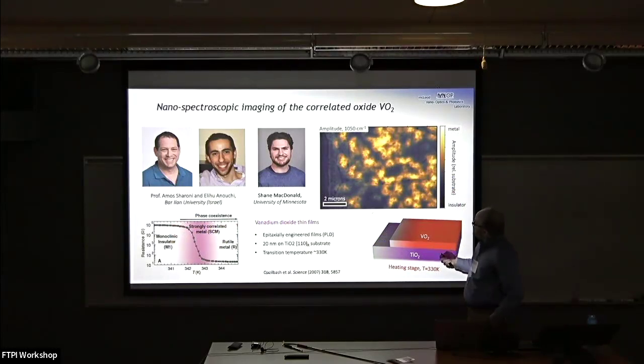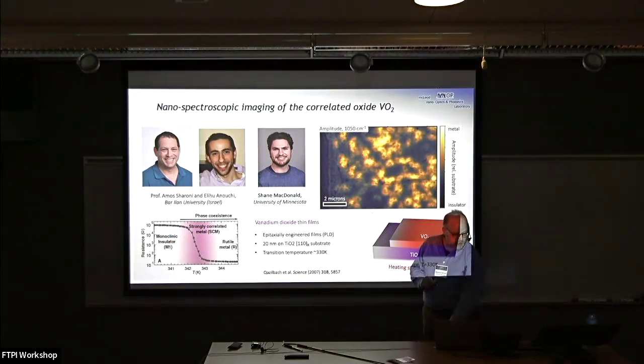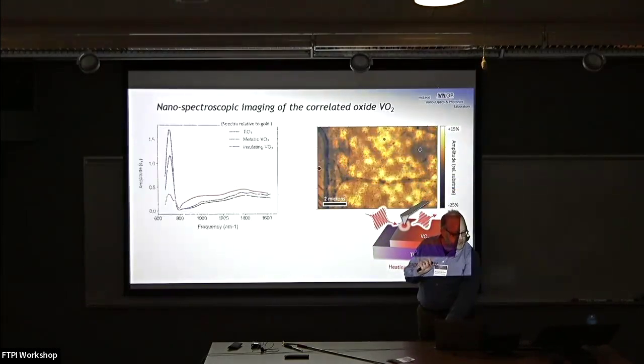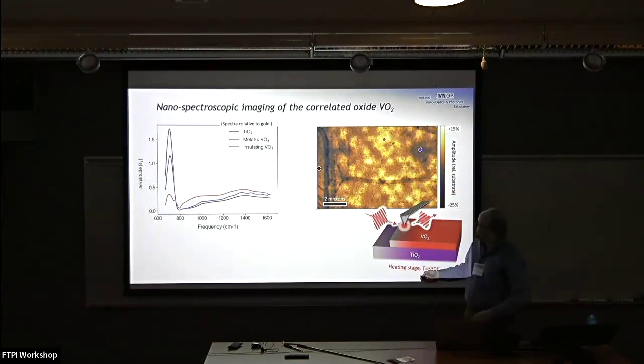So just to round out this example, VO2, our nice Drosophila here, demonstrating this at room temperature. We have our insulator metal transition that we've heard a great deal about already. We can acquire images all day long, but let us instead image at a variety of different frequencies. So these are point spectra acquired on 3 different regions at a snapshot energy: an insulating VO2, a slightly metallic VO2, and the substrate. And I'll speak in a moment about these optical contrasts right here.